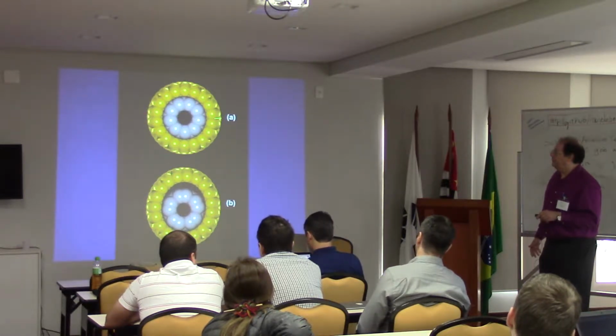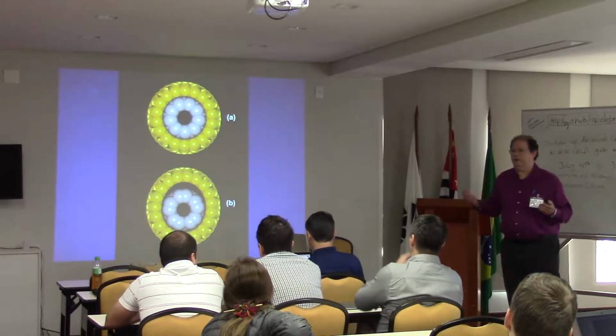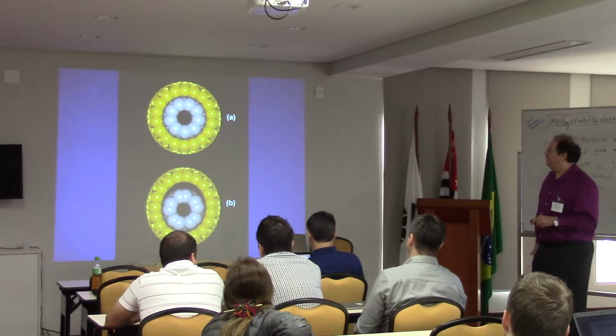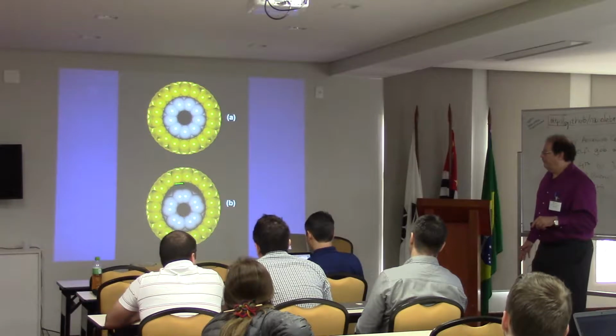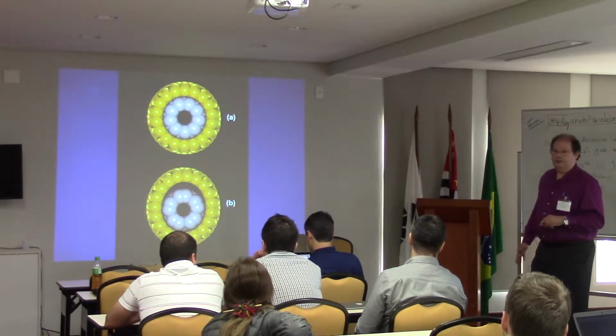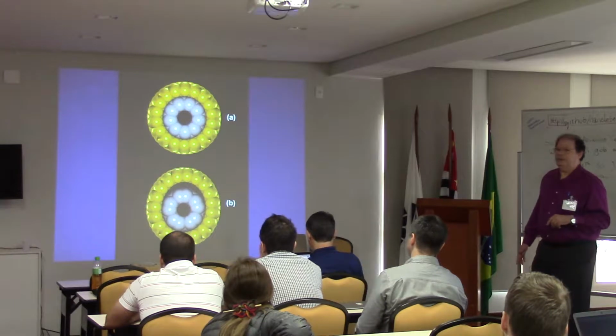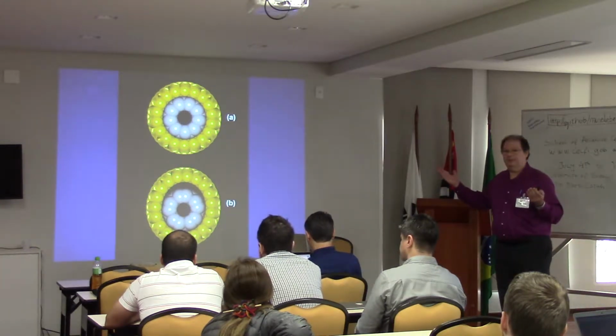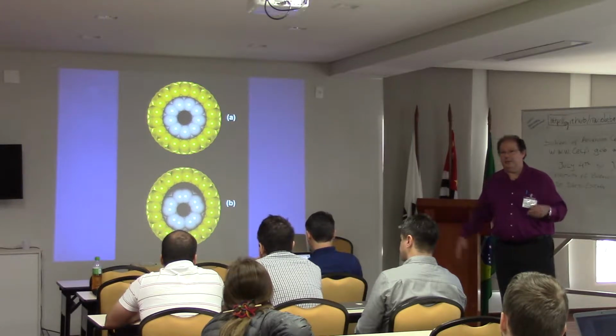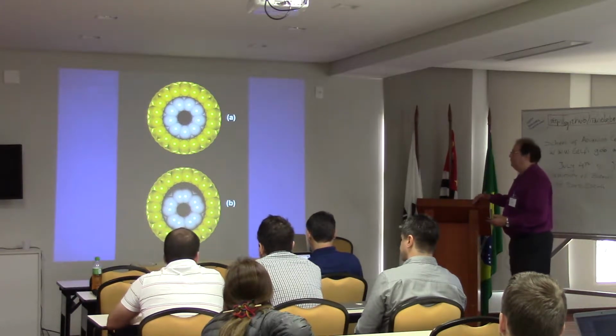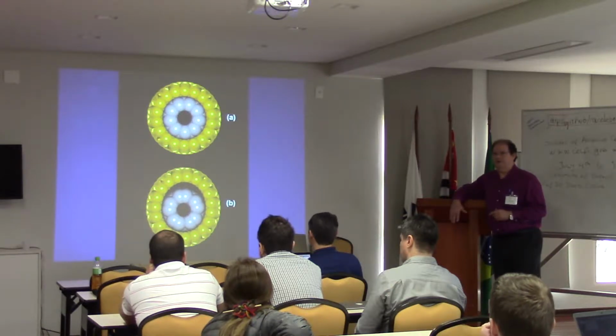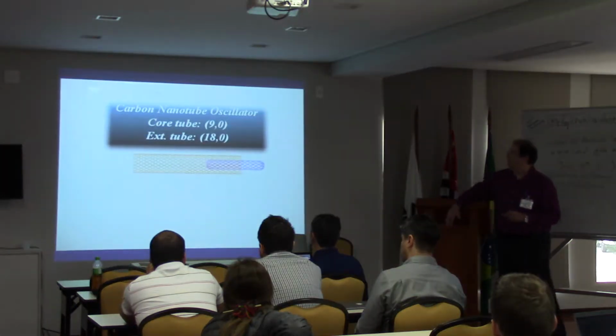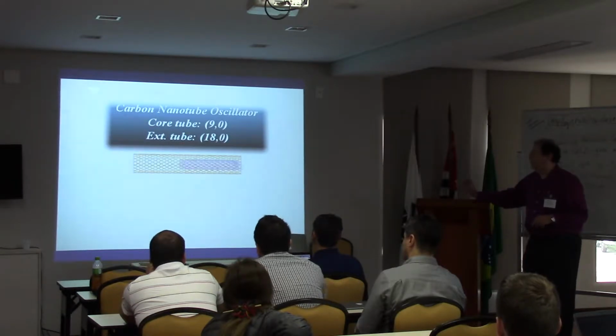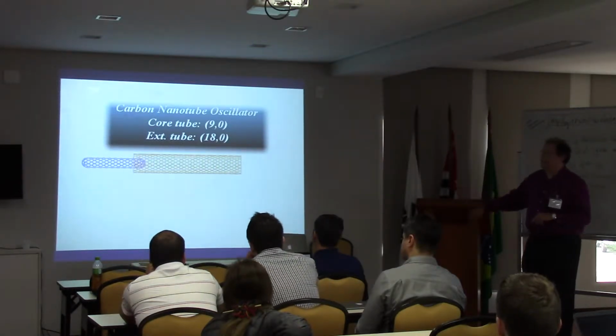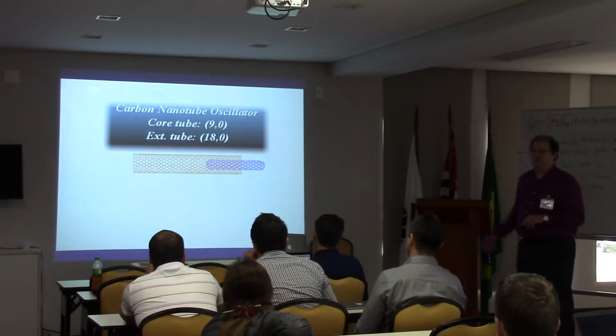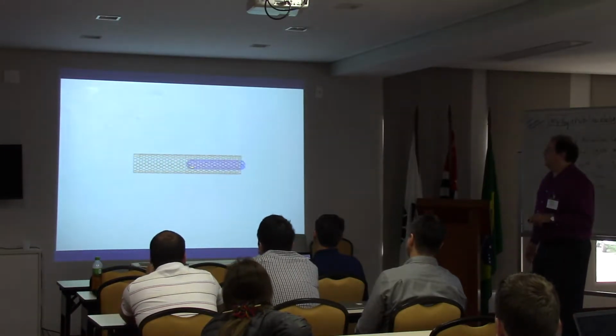In this case, we noticed that not any combination of tubes would produce a sustained oscillator, because if there is some free space here, it doesn't work. This is beyond the experimental capability to distinguish between these cases. It is a sub-angstrom resolution that is not available even for the best electron microscopes. So in this case, simulation provides useful information about the dynamics of the system. When we did the simulation for the perfect matching, we can see that the sustained oscillation can go on for very long times, and also at high frequency.